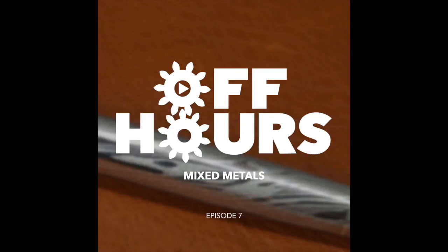It's perfect for making a couple of rings out of, but for a pen, it doesn't get you very far. So this is made out of 316 and 304 stainless that have been fusion welded together. I took a torch to it, heated it up so that it was yellow hot, used a hammer, and drew it out into a longer, thinner cylinder. I took it from 1.125" down to maybe 650 thou in diameter.